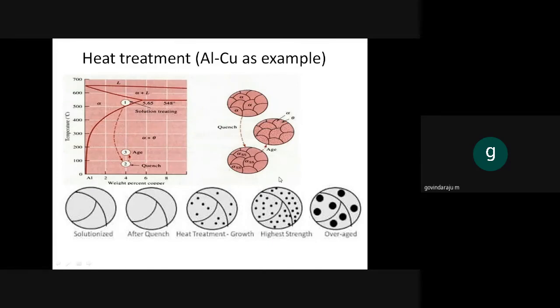For example, pure aluminum has a strength of around 70 megapascal. Aluminum copper alloy, what we are talking about, if you only do casting, it is around 100 megapascal strength, only 100 megapascal. But if you do all this heating to this temperature, quench it, again heating at 160 degrees Celsius, and control this theta precipitate, it can have a strength of 400 megapascal. So from 100 megapascal of this alloy, we made 400 megapascal, 4 times more strength we got. This is how we get high strength material for aircraft.